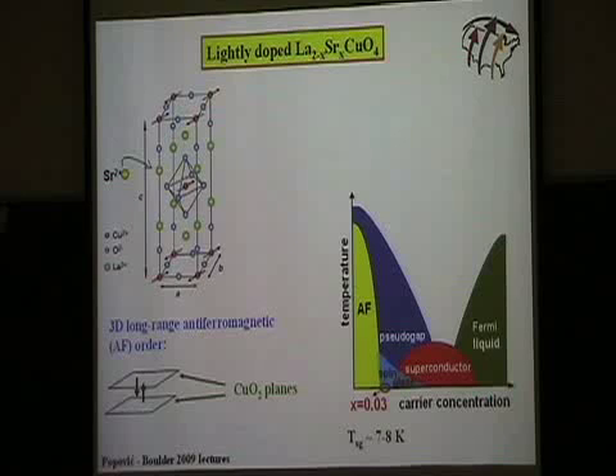When you say here the dopants are also substitutional? Yeah, they substitute for lanthanum. So this one has valence 2, this is 3, so it donates one hole to this copper oxygen layer. Now the undoped material is an antiferromagnetic insulator. Now it turns out that in each copper atom you have a spin, and they are antiferromagnetically ordered in the plane.